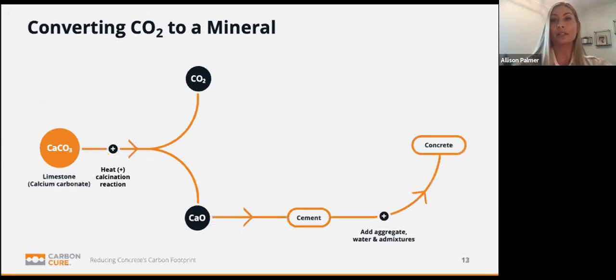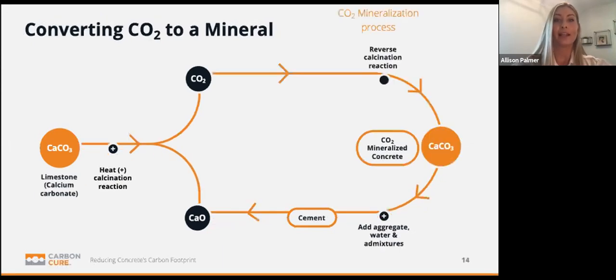So then we ship our cement off to Ozinga, and they mix it with sand, aggregates, water, cement, other SCMs to form our concrete. And now this is where we come in. We're introducing that precise dose of CO2 into the mix during mixing, just like an admixture. It gets dispersed throughout the mix and warms up to room temperature as a gas. And as soon as that CO2 becomes a gas inside of the wet concrete mix, it's like a magnetic attraction that occurs between the CO2 and the calcium from the cement. These two molecules want to bind together and return to their original state of calcium carbonate, aka limestone.